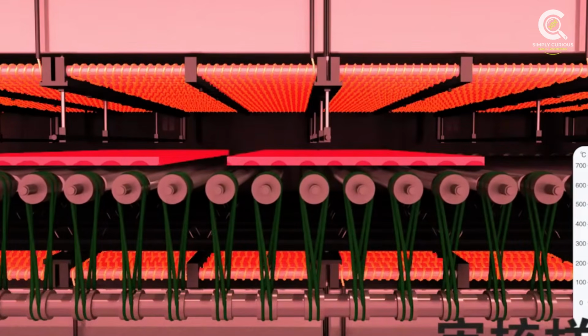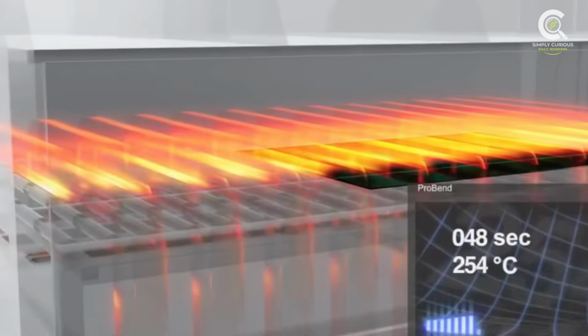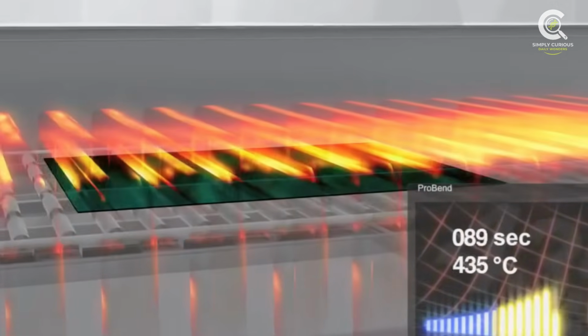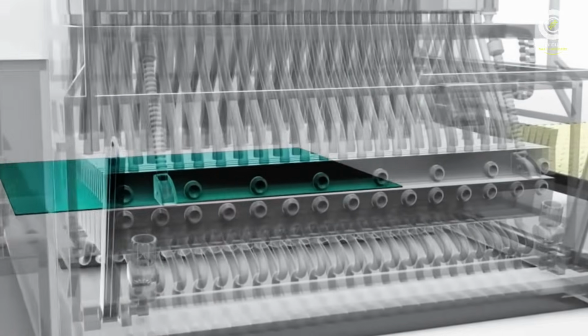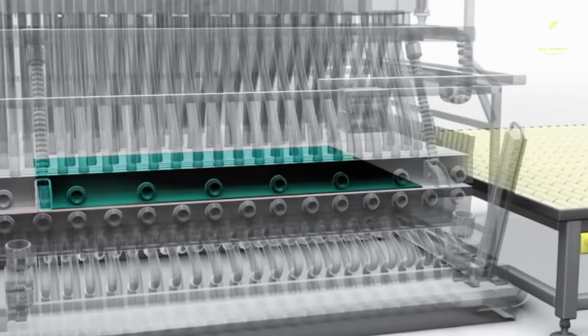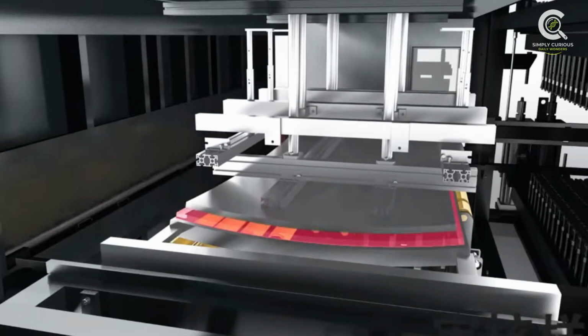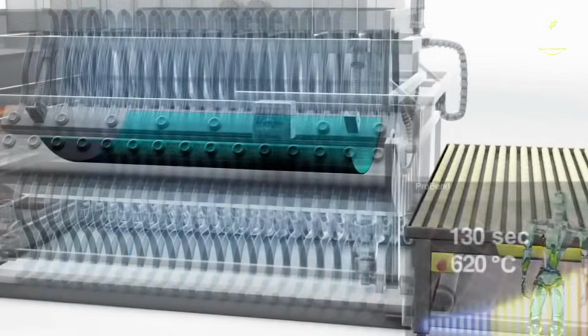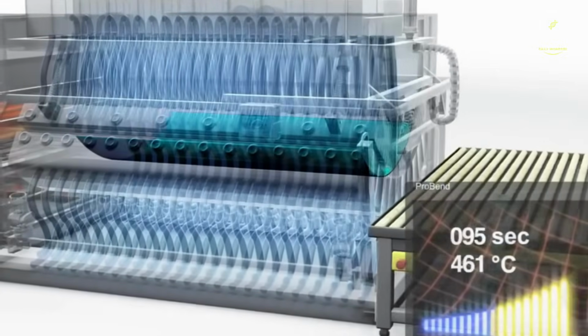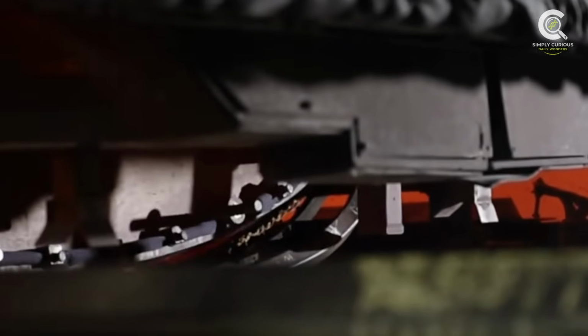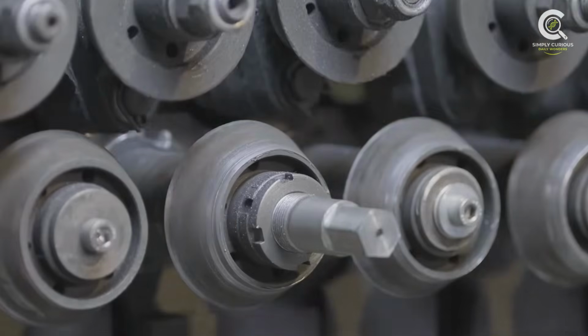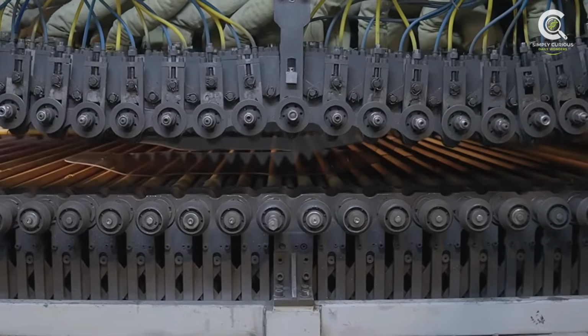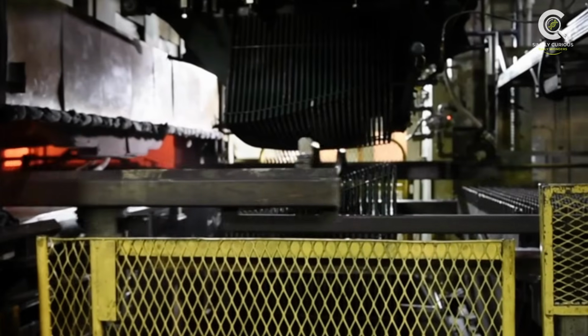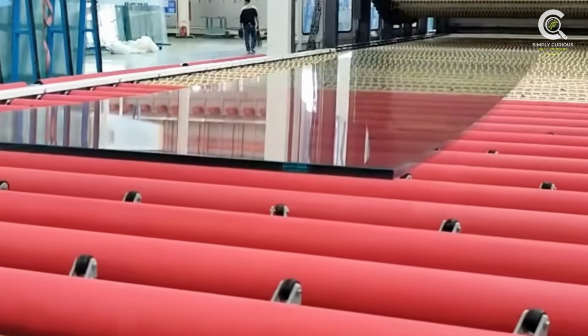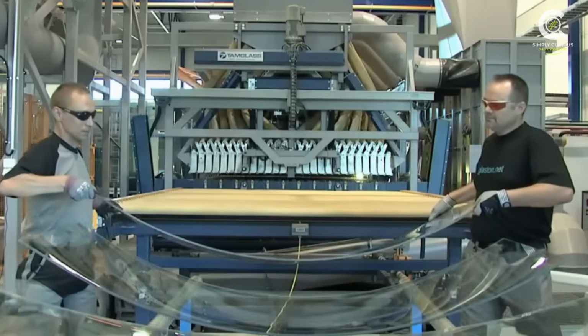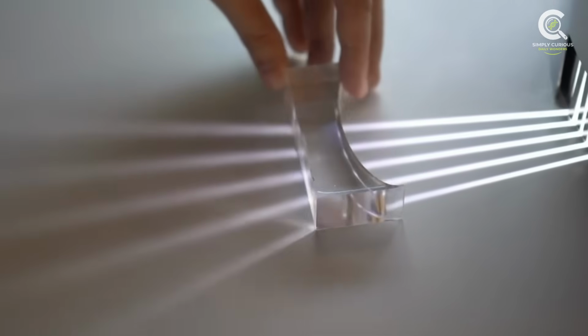Modern windshields are curved to match a car's aerodynamics. To get that shape, the glass goes into a furnace until it's soft enough to bend. Because black absorbs heat faster than clear glass, the solid ceramic frit at the edge gets significantly hotter than the center, creating a sharp thermal cliff. Physically, hotter glass wants to expand while cooler glass resists. This tug-of-war creates intense internal pressure, known as stress. If that temperature drop is too abrupt, the glass will fracture during manufacturing or warp, causing optical distortion that ruins visibility.